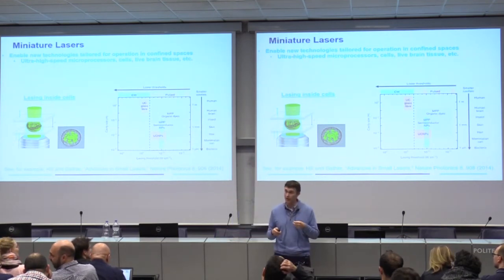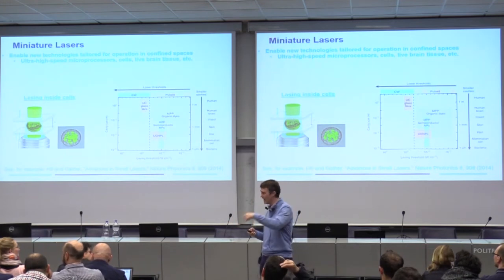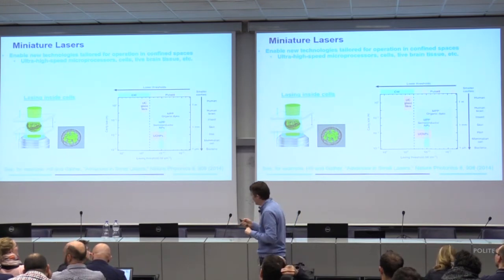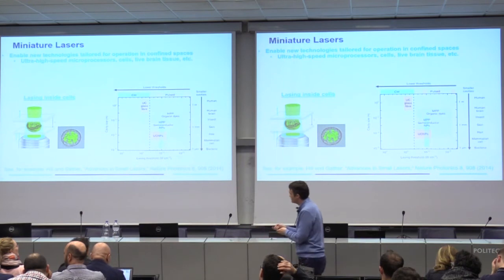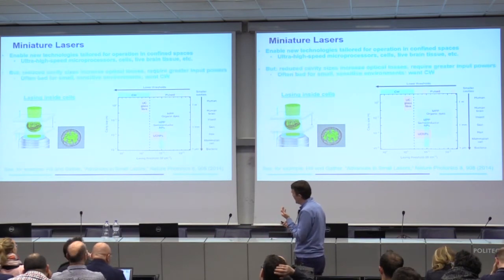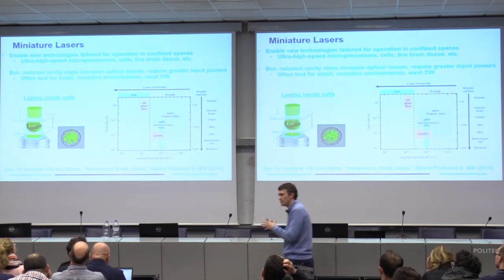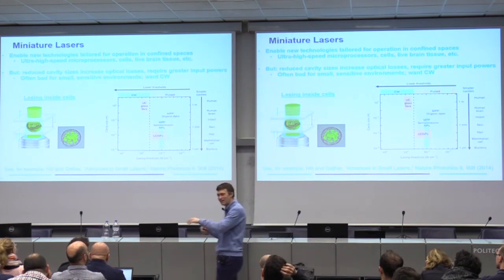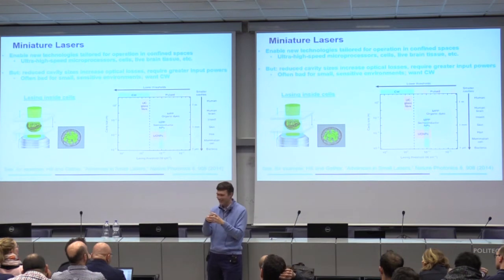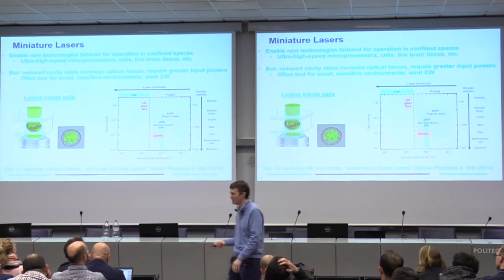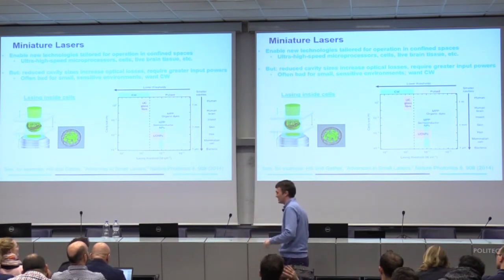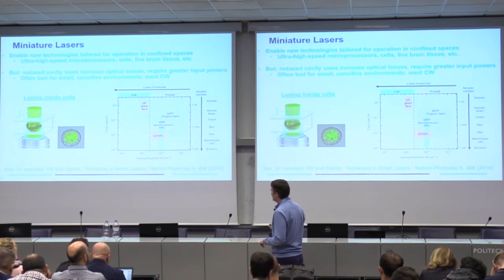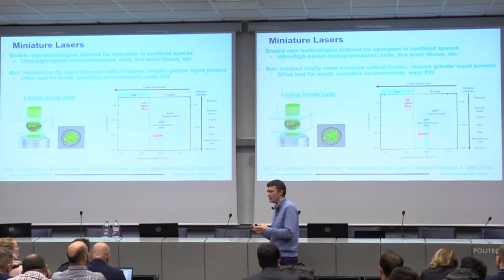You want to put little upconverting lasers inside your brain for optogenetics, things like that. The main issue is that as you make lasers smaller, we learned about this in our last talk, you have more and more losses. Light doesn't like to be confined into these tiny, tiny volumes, and you get scattering losses and bending losses and everything else. And so what that means is that unfortunately, as you make lasers smaller, you have to pump them harder and harder to get them to lase.